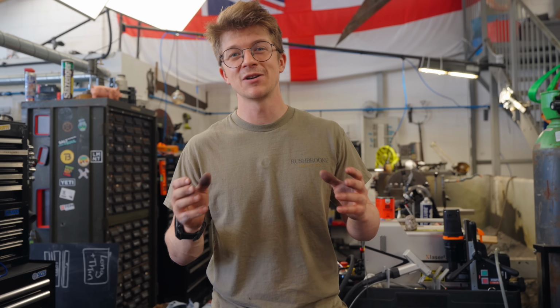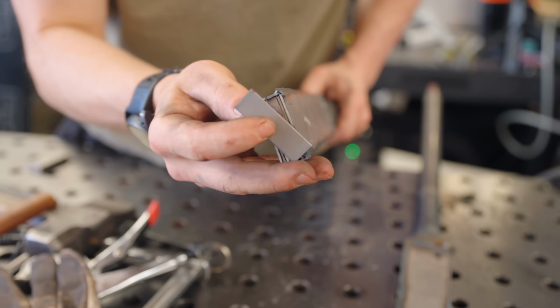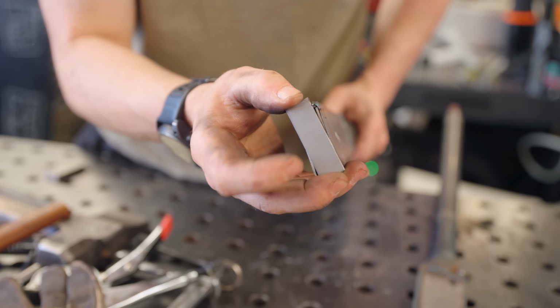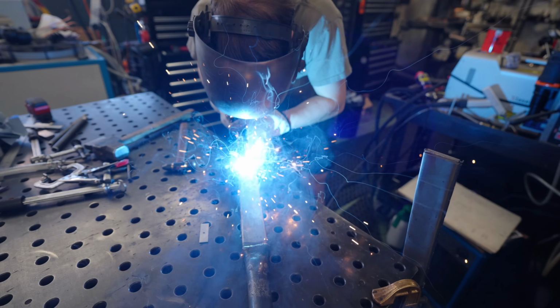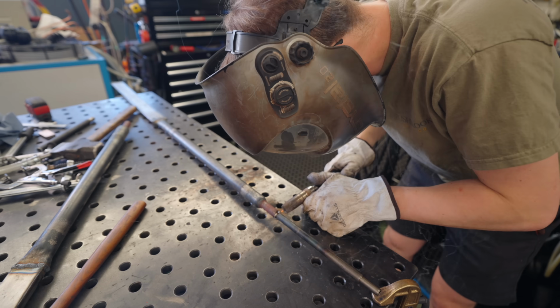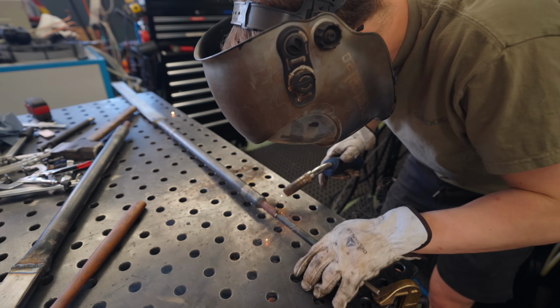Both of our samples have a 0.2 millimeter thick nickel interlayer to act as a diffusion barrier between the titanium and the steel. We're going to weld a little end cap here with a hole so that the argon can flush through. We're going to weld some pipes on this side so we can hook it up to my argon hose, and hopefully we're going to be learning a thing or two pretty quick.